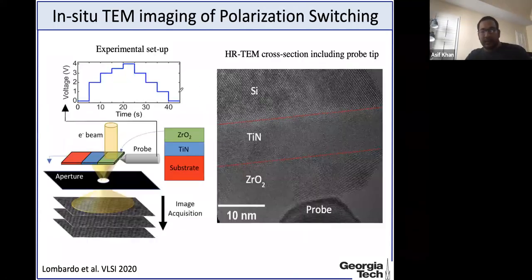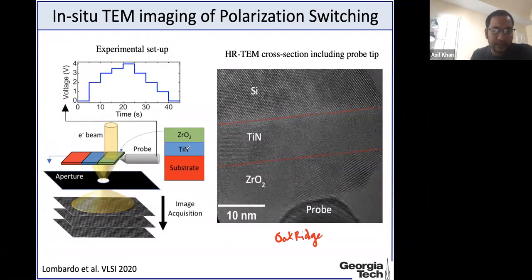All right. Next, one of my students, Sarah Lombardo, did a very cool experiment 2 years back at Oak Ridge National Lab. We took an antiferroelectric zirconia film and did TEM imaging of it with an in situ applied electric field. We took the HRTEM images of the zirconia layer, and while the voltage was applied, we were imaging it at the same time. So this is the zirconia, and we will particularly focus on this zirconia grain over here.